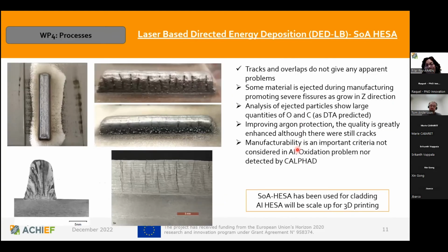In DED, the results are completely different, in the sense that we also have cracks, but these cracks are magnified because of the lack of a chamber to protect the atmosphere. But it's not only the problem of oxidation, because when we increase the protection on the nozzle, we get better performance and better quality, but in any case, we still have these cracks. As you can see here, during the manufacturing, we detected some ejection of material that we can correlate with the DTA. This is a problem that is not only related to the quantity of oxygen in the atmosphere. Because of this, and the time of the project, we decided to go ahead, at least for printing, with the Al HESA.